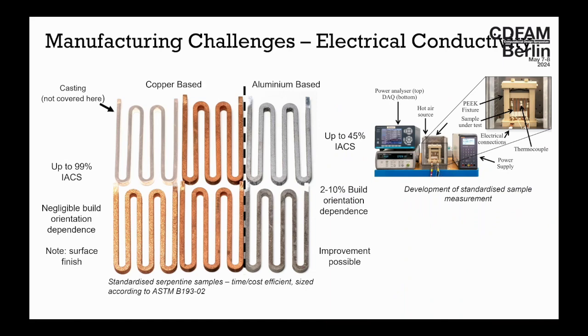Now, a significant challenge is the fact that if I go to 10 different vendors and say, print me this copper piece of whatever, so this is a serpentine sample, or what we've dubbed a serpentine sample, I will get 10 different components back, and they will all have different properties. Same with the aluminium. And so we have had to come up with a measurement standard to allow us to measure the electrical conductivity of components and to work very closely with vendors to understand exactly what the influencing factors are and how we can remove those or minimize those in the process.